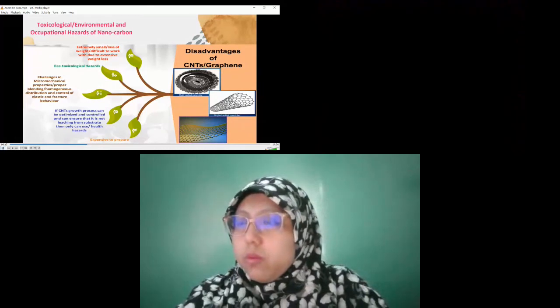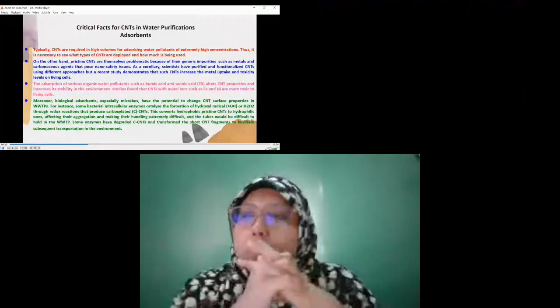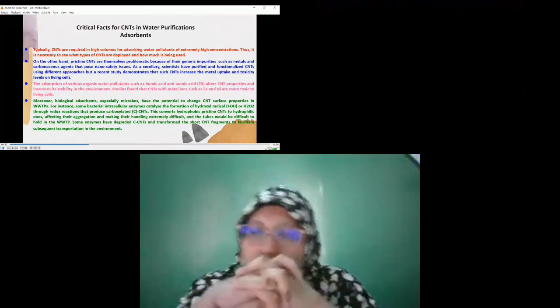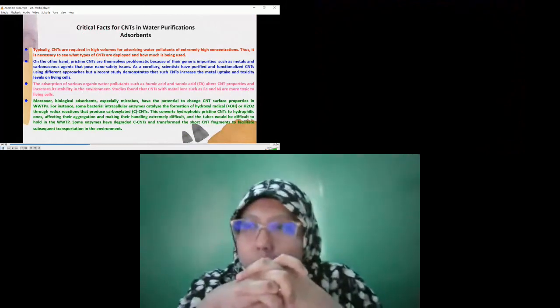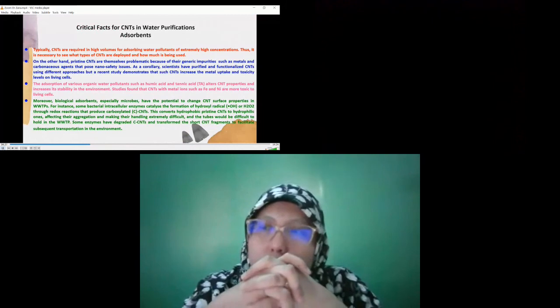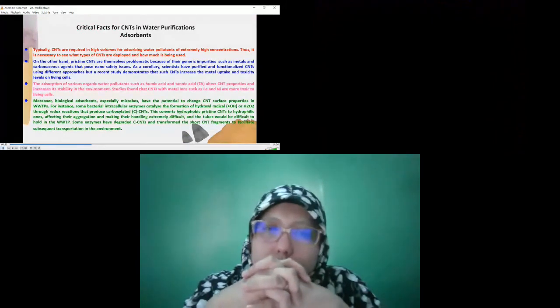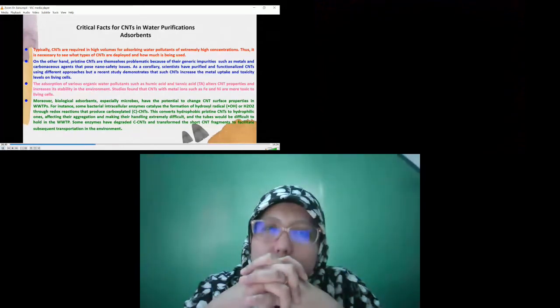If we consider the critical factors for CNTs, if any type of microbe is present, then the CNT surface will be changed, and there will be hydroxyl and hydrogen peroxide radicals, and this will convert the CNTs to carboxylated CNTs, which are hydrophilic in nature, and separation of them from water is very difficult. There are humic acid and tannic acid present in wastewater also. This will change CNT properties, and then they will be too stable in the environment.